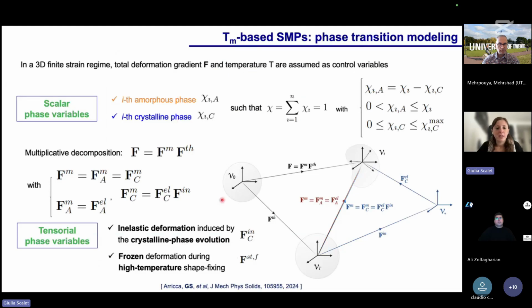Finally, let's just focus also on the modeling. This is a very important part because these multi-phase crystalline networks are not modeled in the literature. So we propose this first model that allows to take into account all the possible conditions, so different polymers within this network with different inelastic deformation contributions, and that are responsible for this two-way memory effect under both applied stress and stress-free conditions.